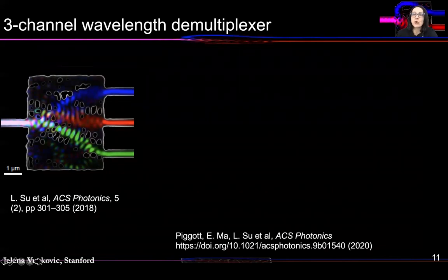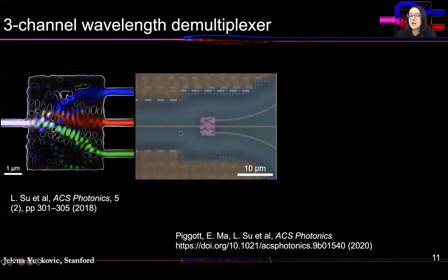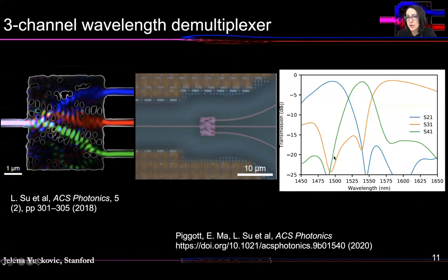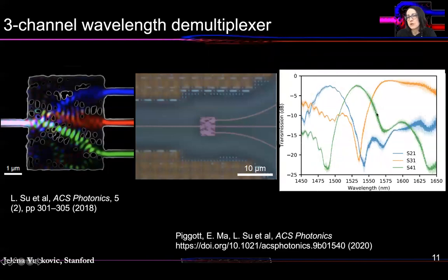Here I'll show you a comparison of a three-channel wavelength splitter, the one that we previously made at Stanford using electron beam lithography and etching. The same device fabricated in AIM Photonics, which you see here in an optical microscope image. Here is the theoretically predicted behavior for transmission through the structure for all three channels, and the measured performance for the device fabricated in a foundry shown here. This is not for one device, this is for many devices that we measured, and they all performed the same despite some fabrication errors.